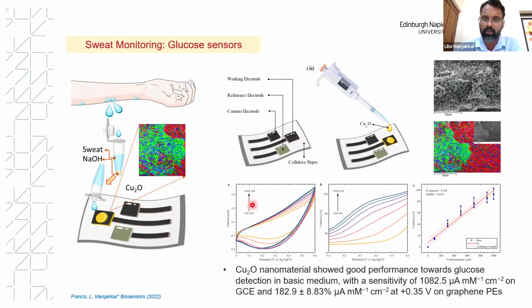And then you can see here the performance of the sensor using Cu2O as a sensitive electrode on top of a glassy carbon. We monitored initially the cyclic voltammetry and other parameters with various concentrations from under micromolar to 1000 micromolar. We varied the sweat glucose level, and you can see from here that in a basic medium, with a sensitivity of almost 1082.5 in a glassy carbon and 182.9 micromolar per centimeter square in a printed electrode.